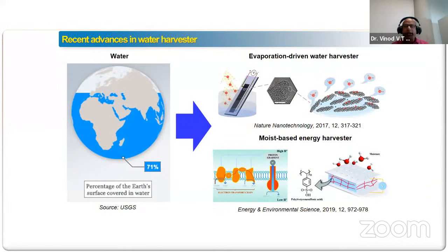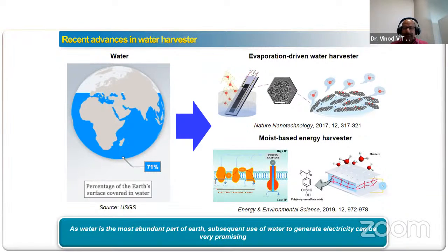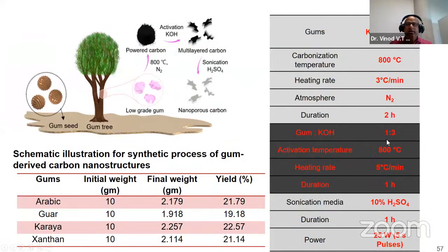So there is a lot of work going on recently on how evaporation driven water harvesters can be prepared and how we can use them for energy applications. So this is a scheme of the work we carried out. We used the gum material from the tree and made the powdered carbon at 800 degrees Celsius in nitrogen atmosphere, and then activation with potassium hydroxide and sonication with sulfuric acid. Finally we made this nanoporous carbon.